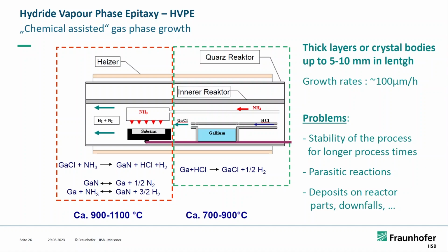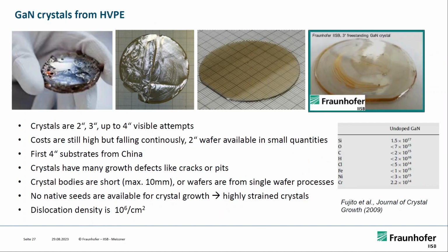You have some chemical assisted gas phase growth, which means that you add chloride and carry it as gallium chloride to the growth surface. You carry the gallium chloride coming from some source, you add the ammonia, and you deposit the gallium nitride at the substrate. This is the principle, and now you see what happens, how the crystal looks.